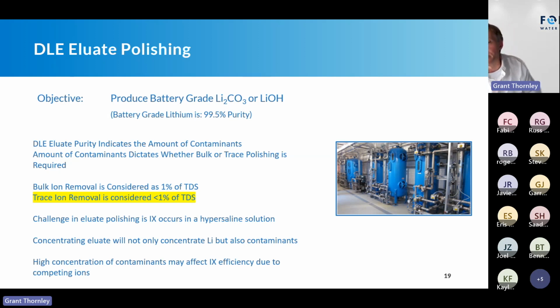And what we mean by battery grade, not technical grade, is battery grade requires a purity of 99.5%. That means that the bulk of the lithium carbonate or lithium hydroxide is lithium with very, very minor or trace contaminants within the final product. So this is why polishing is such a critical component: in order to achieve a battery grade lithium product and command a very high return, I think it's going around 40,000, maybe 60,000 per metric ton of lithium carbonate equivalent right now. In order to realize that, you've got to get it to battery grade.